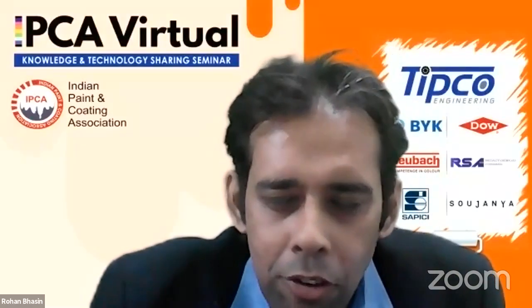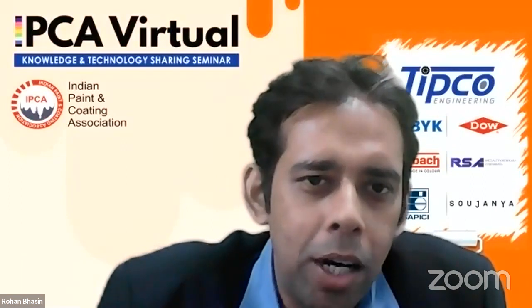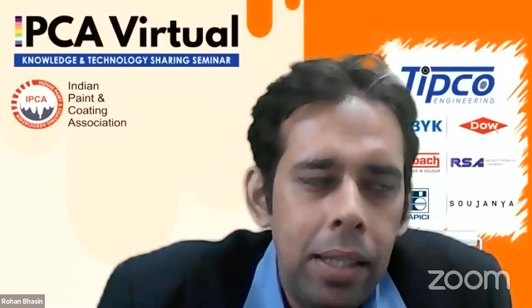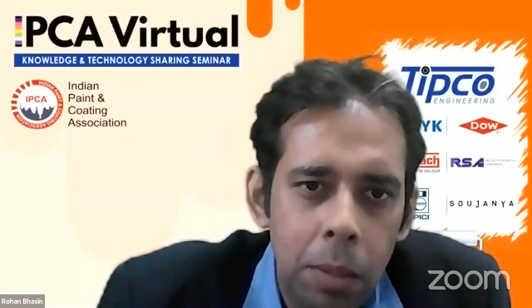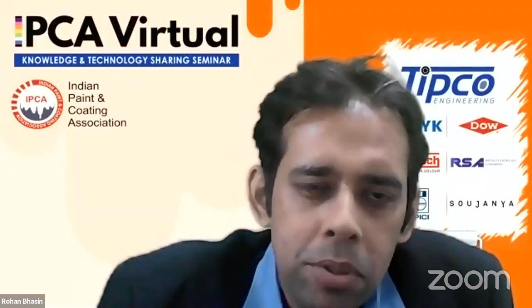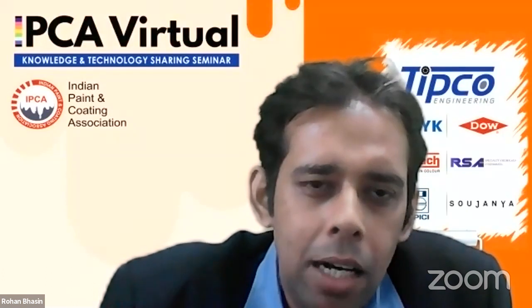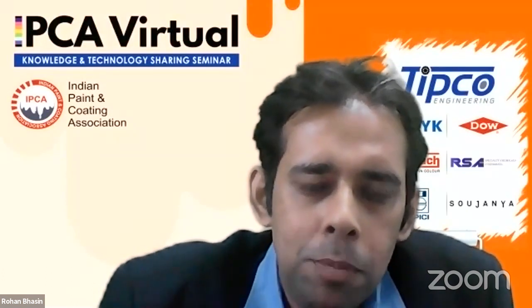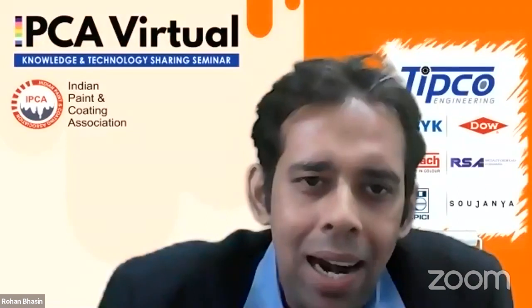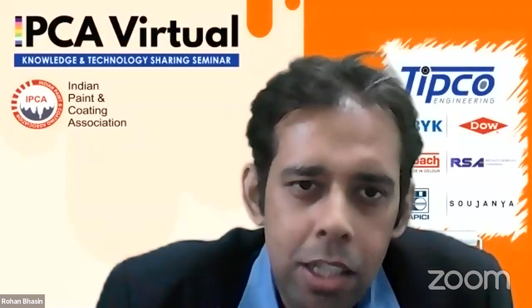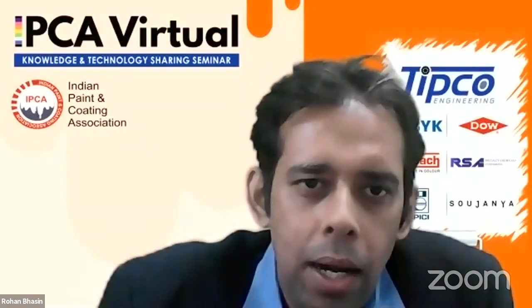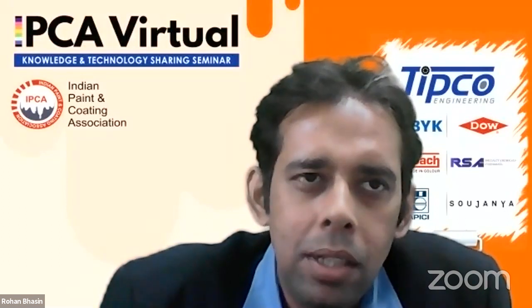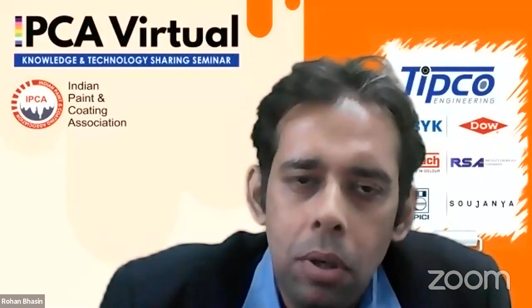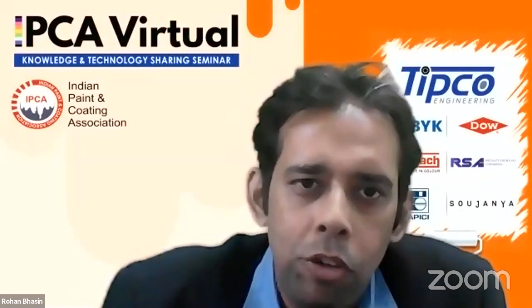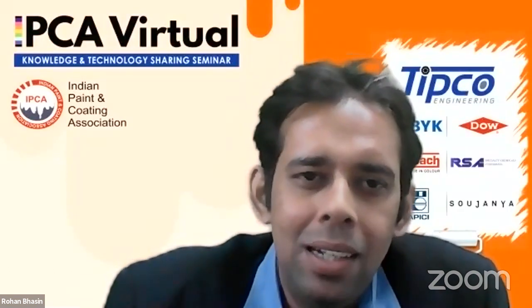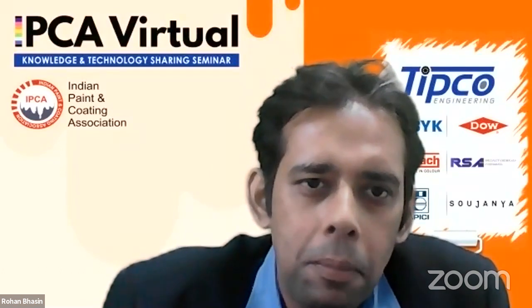One specific question from my side is regarding the HASE thickener, your DR130. I think it goes in high PVC systems, let's say in a product like distemper. What I have observed is that sometimes when we don't get the desired viscosity to match the release specification, it is a very normal thing to add thickener to get to the release specification. But once we do that, after a period of time, I have seen there is a problem with the stability of the product, or it even leads to gelation over a period of time. So could you explain to me the real reason behind this problem?